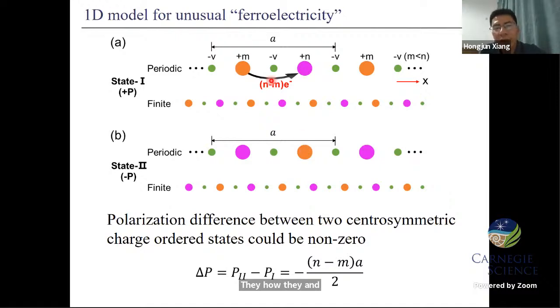We found that going from state 1 to state 2 can be achieved by charge transfer. For example, we transfer n minus m electrons from this site to this site, and we can obtain state 2 from state 1.